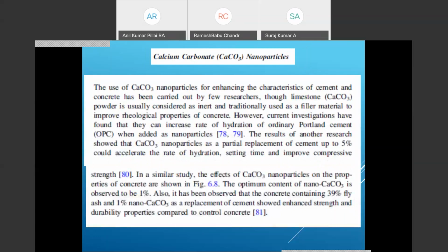Calcium carbonate nanoparticles, it has been found that they accelerate the rate of hydration and improve compressive strength. So calcium carbonate nanoparticles improve the compressive strength. They also accelerate the rate of hydration and the setting time. The optimum content of nano calcium carbonate is observed to be 1%. It has been observed that concrete containing 39% of fly ash and 1% of nano calcium carbonate as replacement of cement showed enhancement in strength and durability properties compared to the control concrete.